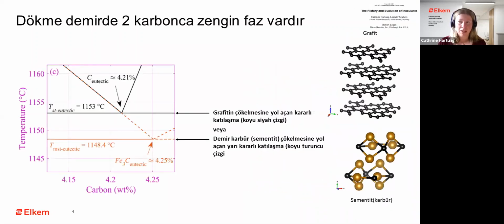So in this slide, we take a close-up of the eutectic point. The eutectic point represents the transition from liquid to solid. For cast iron, what happens here is a simultaneous nucleation and cooperative growth of the iron-rich phase, austenite, and the carbon-rich phase. Now in cast iron, the carbon-rich phase can either be graphite if it solidifies according to the stable system, which is represented here with the black lines, or it can solidify in the form of cementite or iron carbide if it solidifies according to the metastable system.